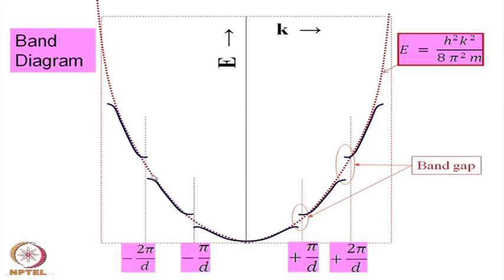So, we have bands of energies, and in between the bands there are forbidden energy levels, or band gaps. This is the main outcome of the band model of solids, and we will see later on that this band model can explain many properties and the behavior of different groups of solids having different ranges of electrical properties, whether it is conductivity or resistivity.